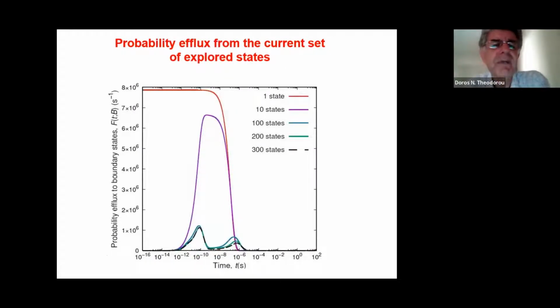What we show here is the efflux of probability from the current set of explored states into other states as we augment this network of states. We start with one state, then go to 10, to 100, to 200, to 300 states, and so on. And we explore the efflux of probability from the explored set of states as a function of elapsed time. And what is remarkable is that if you incorporate a sufficient number of states or minima, you see that the shape of this curve of the probability efflux as a function of time converges into a certain form, which is characterized by well-defined maxima. So you have a peak, for example, at 10 to the minus 10 seconds, and another peak at 10 to the minus 6 seconds. And these reflect certain molecular processes occurring within this glass.